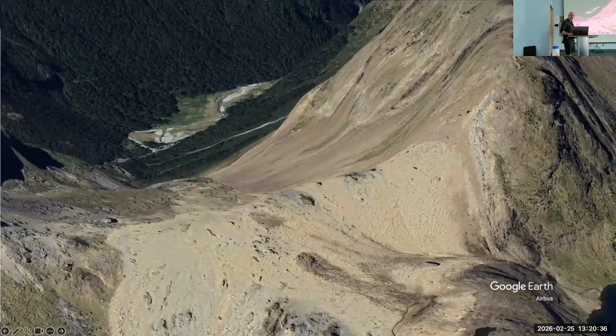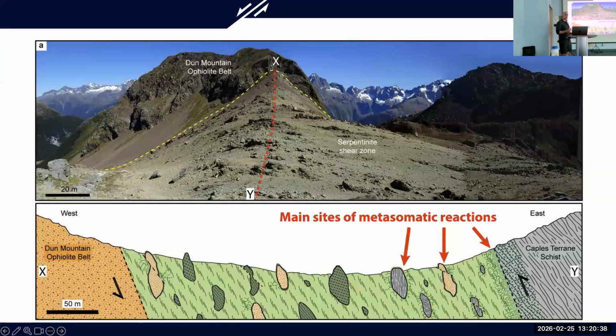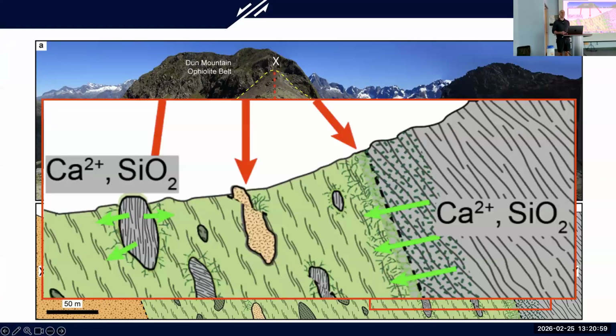And if we look at a cross-section of what that might look like, we have what we call a shear zone, a zone in which shear has been accommodated. It's a really intense mixing zone where components of either side, the serpentine and that calcium silica rock, are being combined together. And this is where we can have these metasomatic reactions that will produce our nephrite. So we're adding our silica and our calcium.